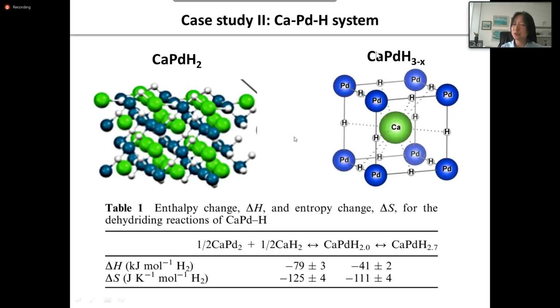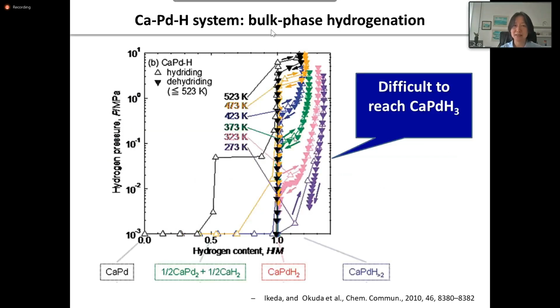People are trying to make CaPdH3, because we want to increase hydrogen content in the system, but it's very difficult. If you look at this isotherm, the y-axis is hydrogen pressure, and the x direction is hydrogen content. It is very difficult to achieve hydrogen content higher than 2.6. So that is in the bulk phase state. However,